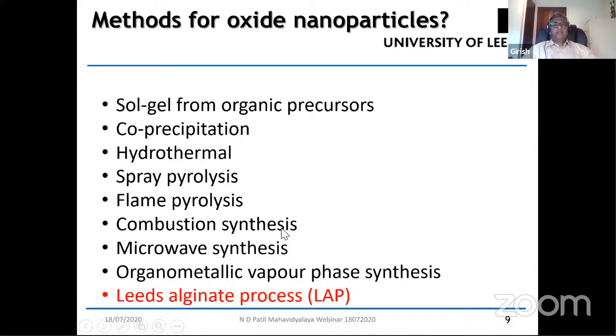Combustion synthesis again is interesting. I'll combine these two, combustion and microwave synthesis, because the problems faced in combustion and microwave synthesis are similar. They are economical processes and could be scaled up. However, the main problem with these techniques is thermal runaway. In combustion synthesis or microwave synthesis, there is always a possibility of thermal runaway, and that can lead to a wide range of particle sizes in the material that you produce, or sometimes even inhomogeneous materials, and that is not good if you want to apply these materials in technologies.